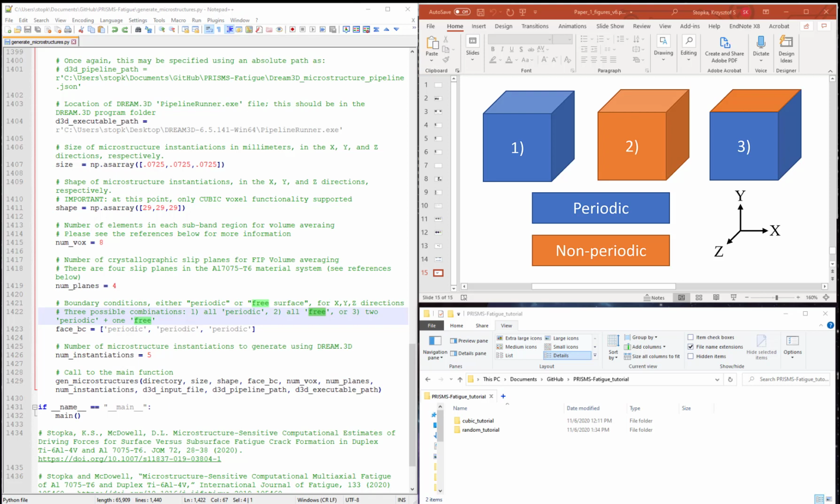However, users will see in the references that some simulations are performed with one set of parallel faces set to non-periodic to emulate free surfaces, while the other two directions are still set to fully periodic. For instance, in the slide here, what this indicates is that in the y direction, the simulation is a free surface, while in the z and the x, it is constrained as periodic. So essentially what this would emulate is a thin film or a thin sheet of material.